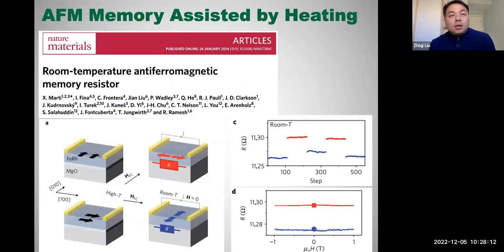In 2014, Ramesh's group at UC Berkeley reported a prototypical device called a room temperature antiferromagnetic memory. They used iron rhodium as the key medium. They used the metamagnetic transition of this material, and they applied a large cooling field to pin the antiferromagnetic spin axis through the phase transition. In this work, they clearly demonstrated that when the current is perpendicular or parallel to the antiferromagnetic spin axis, the resistance